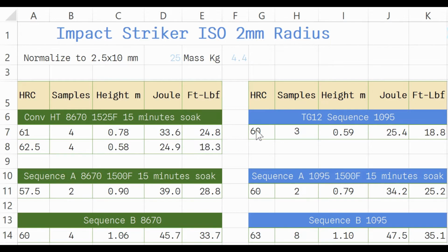and compared to the BluntCut MetalWorks sequence, I only have one set left, which has 3 samples at 60 Rockwell, and that's about 18.8 foot-pounds. So we'll be doing a little extrapolation here. Conventional heat treat at 60 Rockwell may be probably about 28 or so foot-pounds.